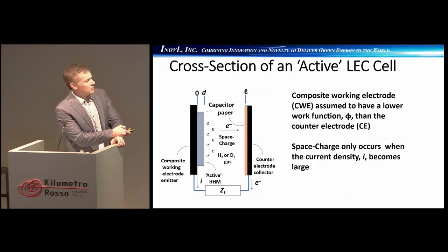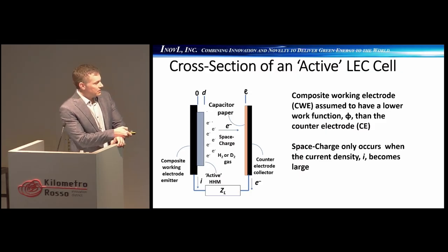All right, a little bit more housekeeping on an active LEC cell. So in this case, you can see our composite working emitter electrode and our active material here, which is emitting the electrons, over towards the counter electrode here with our very fine pore capacitor paper. And you can also see our space charge here. Space charge only occurs when the current density becomes very large, so that's more towards your contact potential difference.